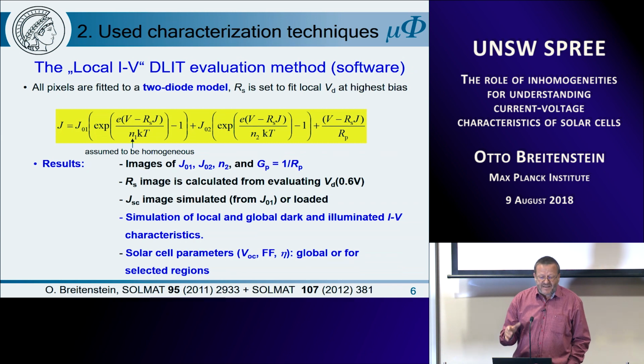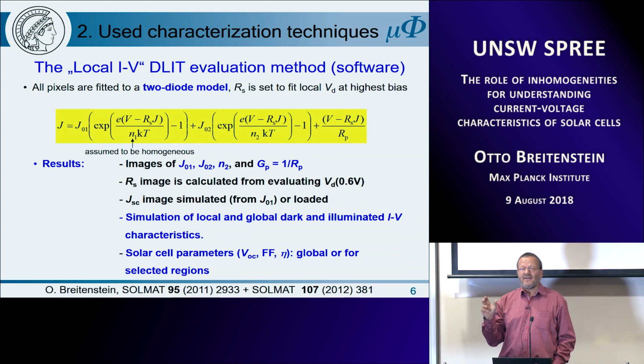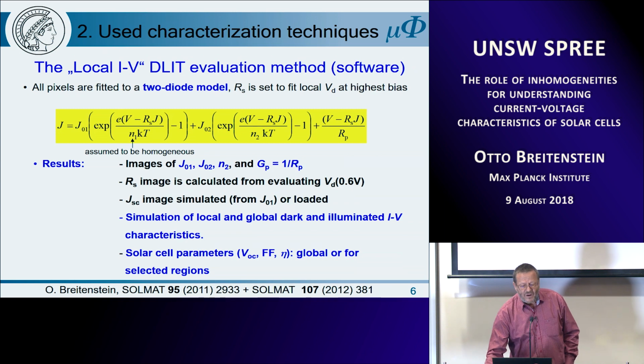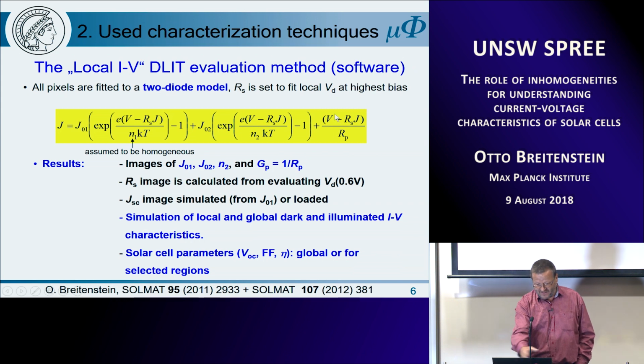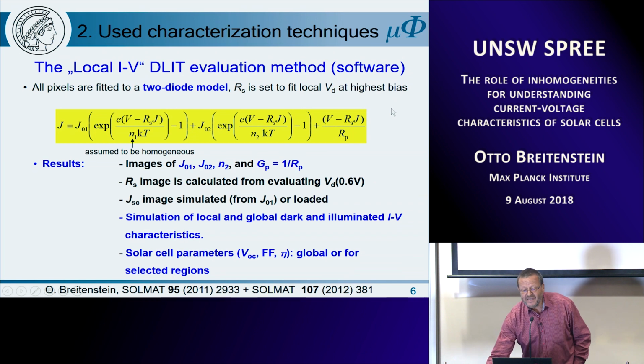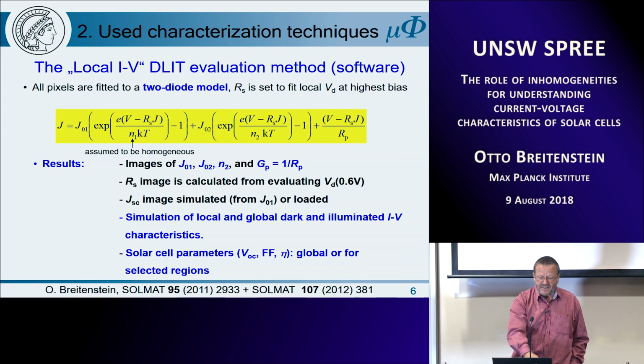The basic thing is the following. We measure dark lock-in thermography images at 4 different voltages, 3 forward biases and 1 reverse bias, and then we fit all pixels to a 2-diode model. This is the 2-diode model: this exponential part of the first diode describes bulk and surface recombination, and this is the so-called second diode, describing recombination in the depletion layer. And this is an ohmic term. So that is the formula for the dark characteristic, including the influence of the effective series resistance RS. So all pixels in the image are fitted to this 2-diode model.